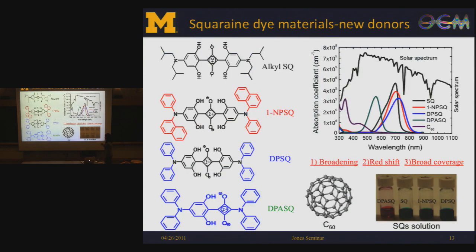Here, we have this material, we have this material, we have this material. So we can see our solar cell has broadened the spectrum coverage, ranging from 300 nanometers to 800 nanometers. Actually, it's 820 nanometers. So this is one of the directions we are working on now, to ramp up the efficiency from 6% to even higher, like 8 to 10%.